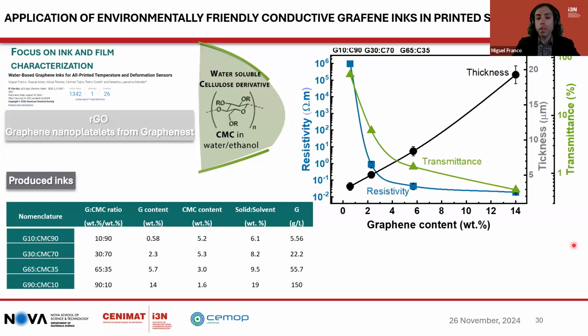It was found the percolation threshold is around 3% in weight, and it can achieve a sheet resistance of 200 ohm per square when above the percolation threshold. In this case, a natural-derived carboxymethyl cellulose, was used in a mixture of water and ethanol. Also, you can see the thickness tends to increase when increasing the graphene loading, from 2 micrometers with a ratio of 10 graphene to 90 CMC, to 19 micrometers with a ratio of 90 graphene and 10 CMC.